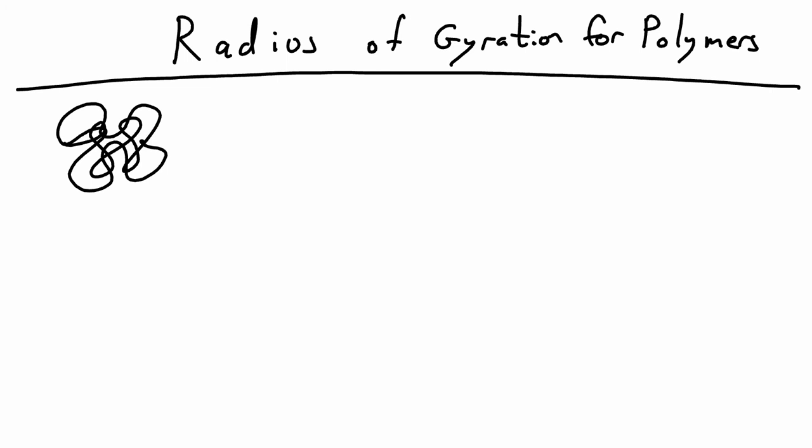Well, it just says that if we went to the center of mass and swung this polymer around, we rotated it, and then replaced it conceptually with a single mass on a string swinging around, that the two objects would have the same moment of inertia. So if we had a little ball of the same mass as the polymer coil and we swung it around, this radius here, r sub g, is the radius of gyration. So this object has the same moment of inertia as this object.